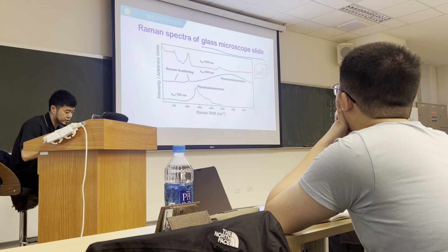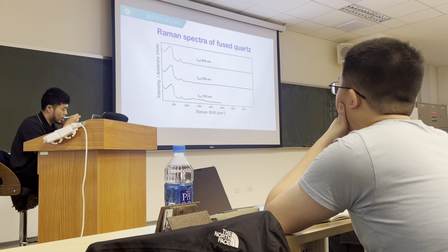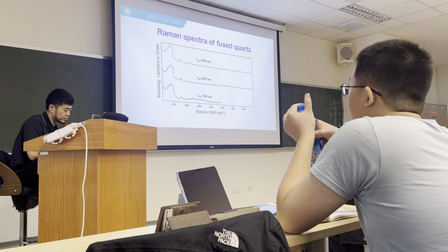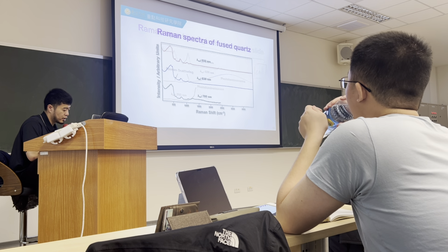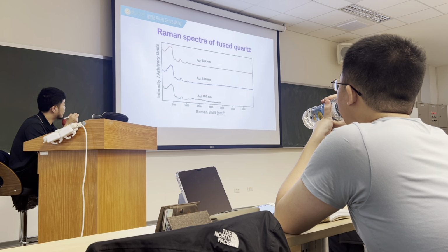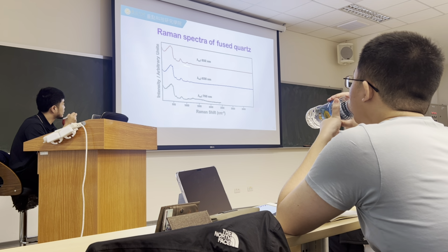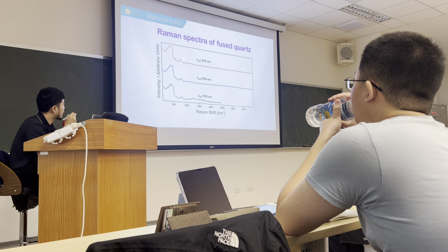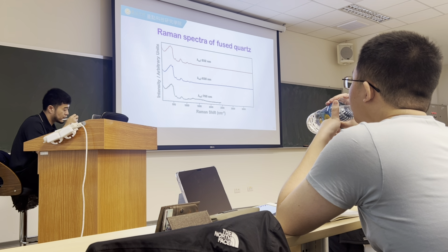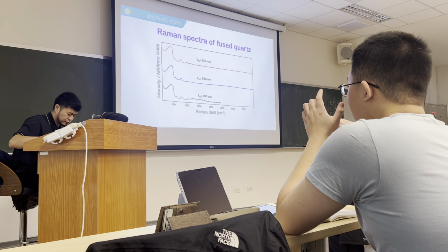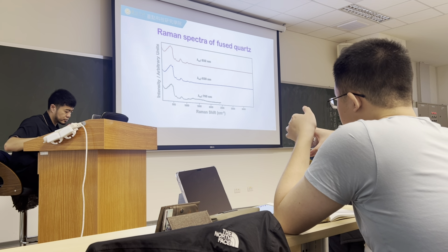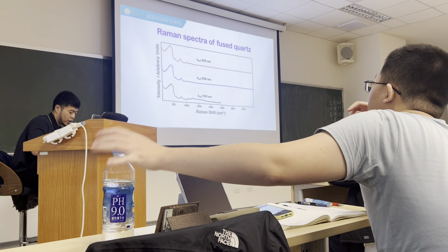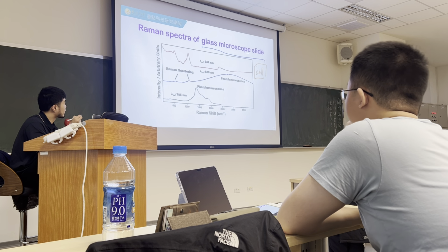The other choice is you should use quartz, rather than glass. As you can see over here, whenever you use quartz, there is nearly no fluorescence in your spectrum, and you can observe relatively obvious Raman scattering compared to when you use the glass slide.